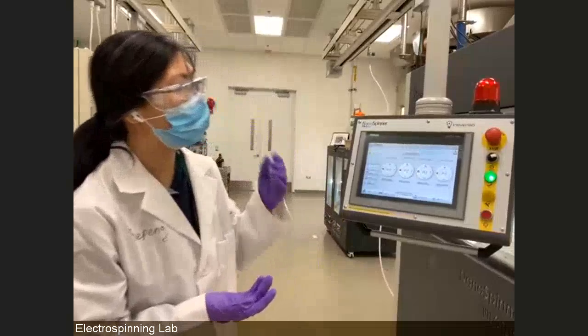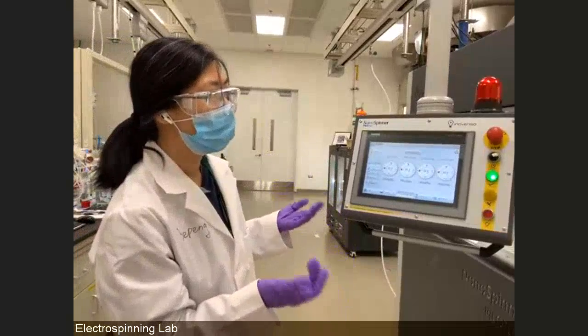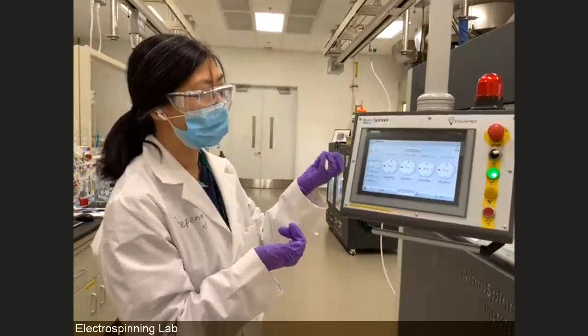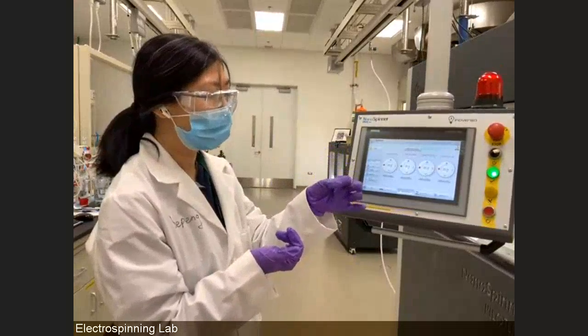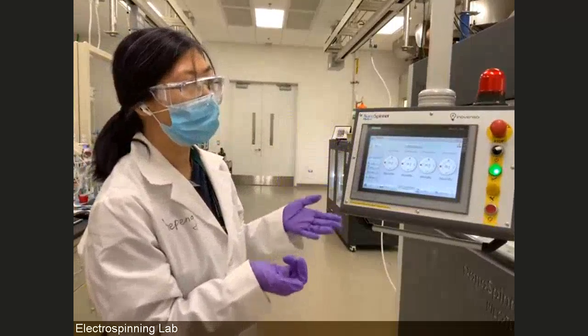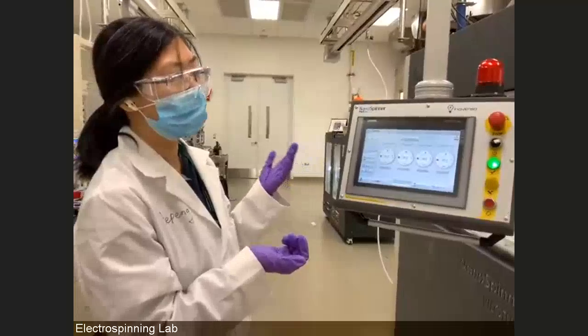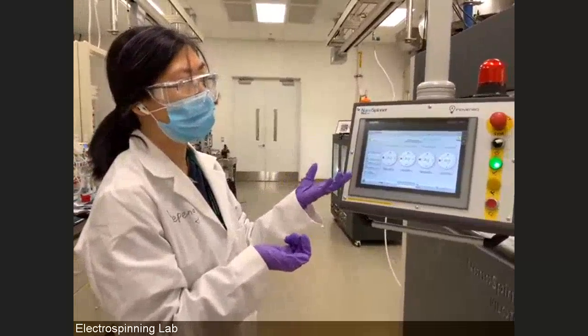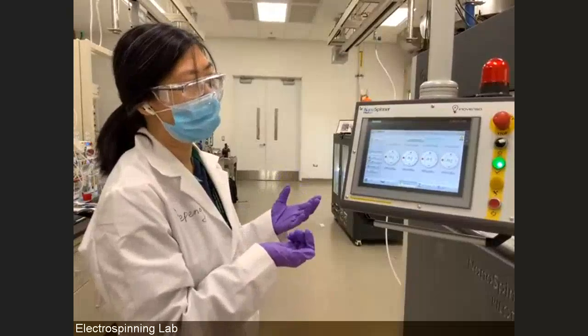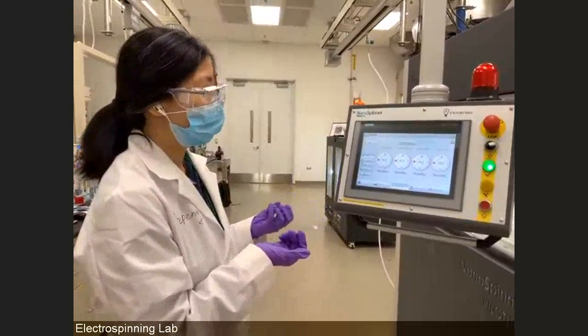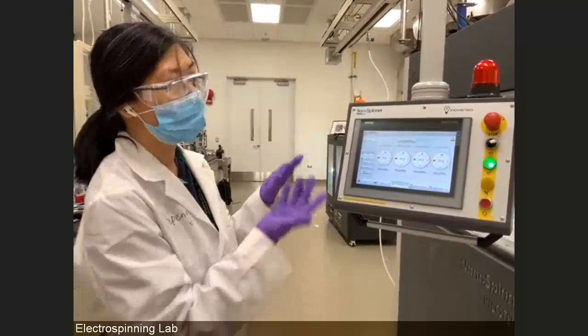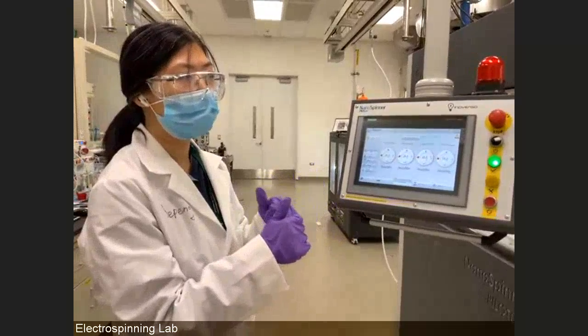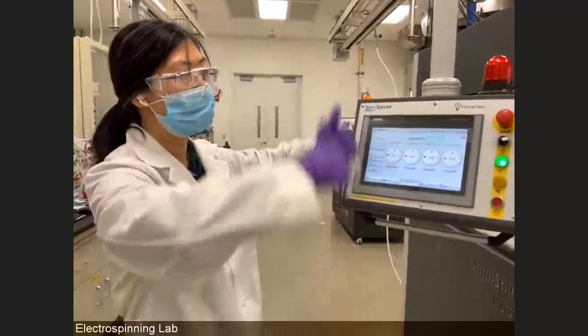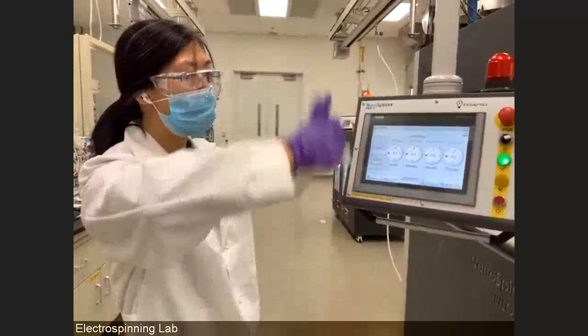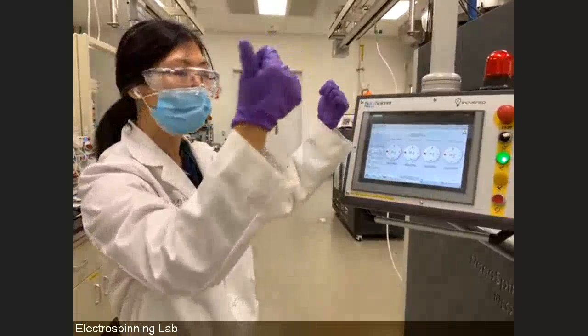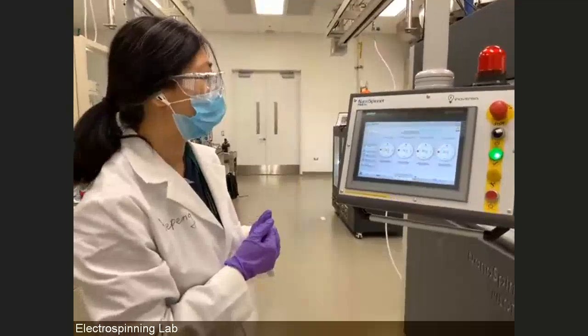The second thing is that when you have a high deposition rate, you need to supply the precursor solution to the nozzle tip. And when you have a thicker nozzle, like what we have here, you have to really control the supply and the consumption of the precursor at the needle tip to make sure that you have a stable spinning process. And also you have multiple jets generated from each nozzle. The third one is that because you use a charged solution, the microjets can have a repelling effect. So instead of shooting to the substrate in a vertical straight way, they try to go in a separate way because of the electrical charge repelling between the jets.